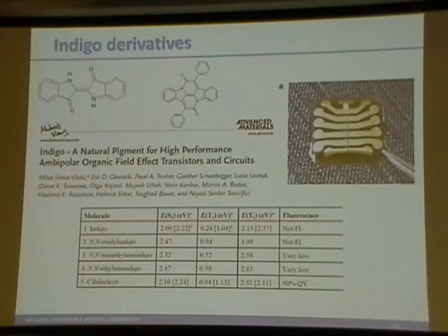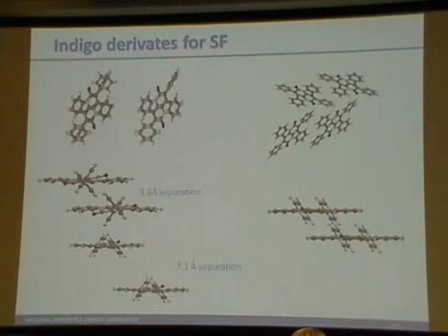Indigo has some issues that we don't necessarily like, so we've settled on a derivative of it. It has roughly the same energetics, it just has a much longer excited state lifetime, so it fluoresces really brightly in solution. So that's one compound that we've been looking at, and so far the results are pretty promising for singlet fission occurring.